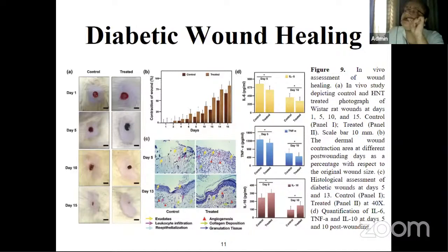The collagen margins were visualized close to the incision layer by day 5 in the test group, and these ultra low biofouling HNTs prevented non-specific protein adsorption on their surface, effectively alleviating foreign body response and resisting the formation of a collagen capsule around the material. So the HNTs may act as an effective molecular sink, curbing excessive recruitment of immune cells and thereby resolving the inflammatory phase quickly, as assessed by the significant increase in IL-10 concentration compared to the control group.